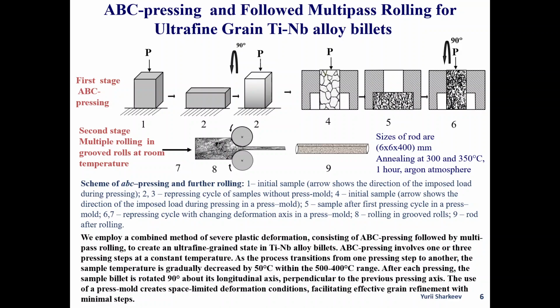We employ a combined method of severe plastic deformation consisting of ABC pressing followed by multi-pass rolling to create an ultrafine grain state in titanium niobium alloy billets. ABC pressing involves one or three pressing steps at a constant temperature. As the process transitions from one pressing step to another, the sample temperature is gradually decreased by 50 degrees Celsius within the 500 to 400 degrees Celsius range. After each pressing, the sample billet is rotated 90 degrees about its longitudinal axis, perpendicular to the previous pressing axis.